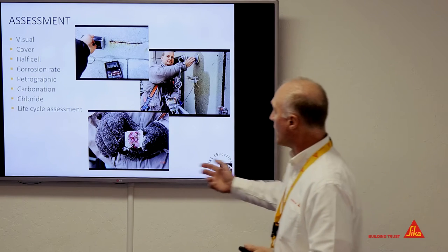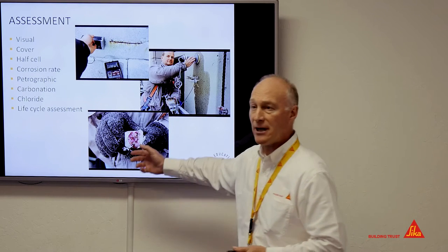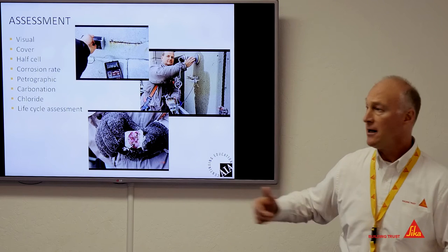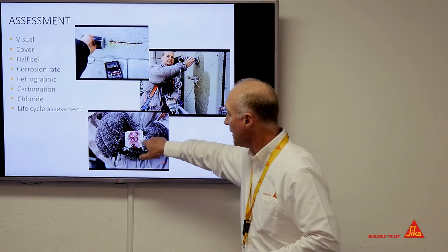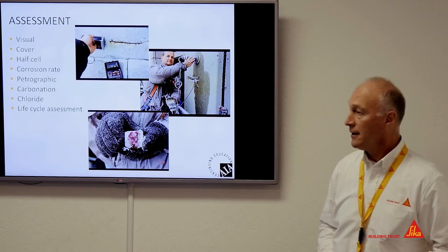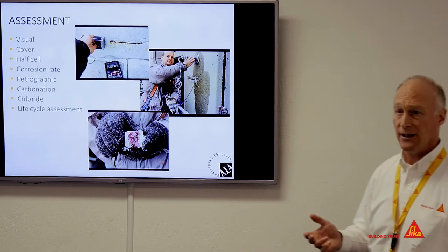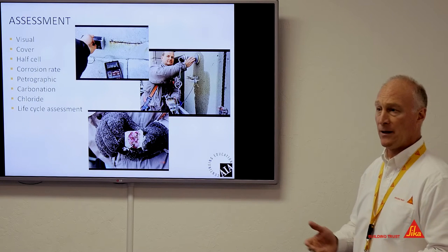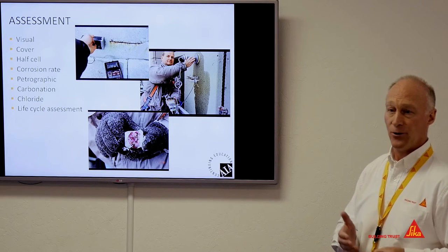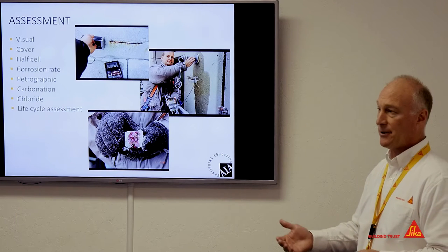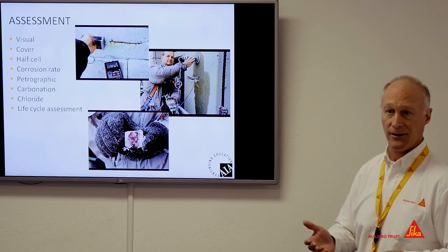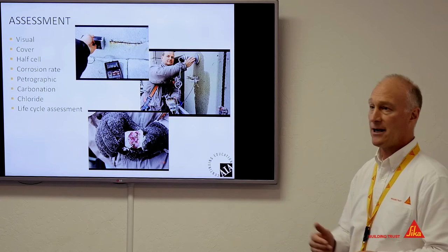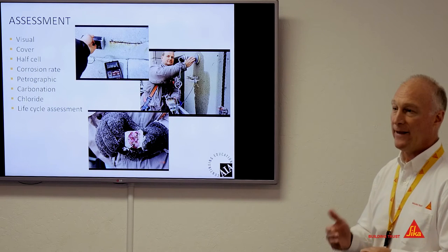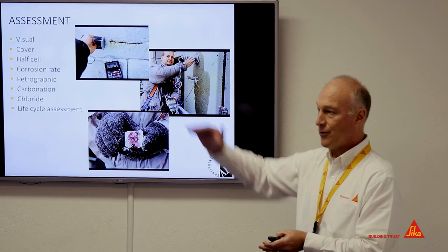They may pull out a core, like they did here, and do a petrographic analysis to have an understanding. In this particular example, this was pulled from a building in Boston that was built in the 70s, and they used chlorides in the mix because the concrete was being placed in the wintertime. So they had cast-in-place concrete with chlorides. They had already cast chlorides into the concrete. So from day one, that building was on a path toward corrosion.